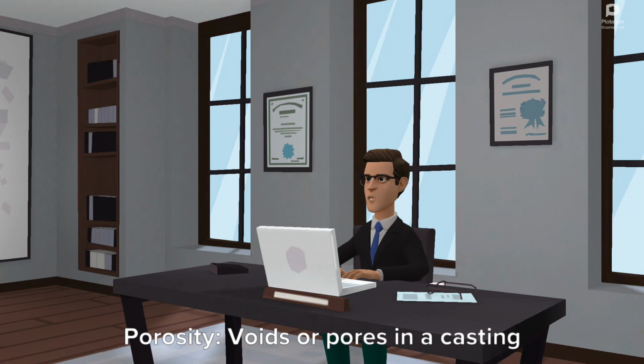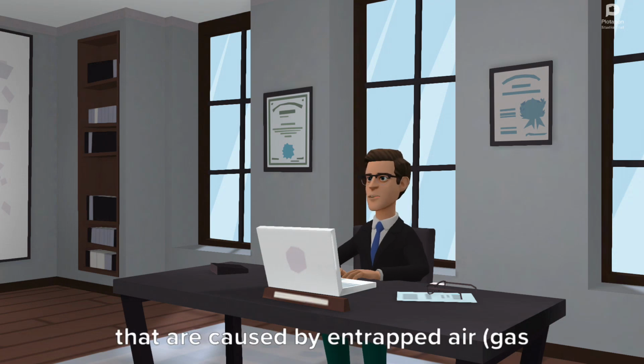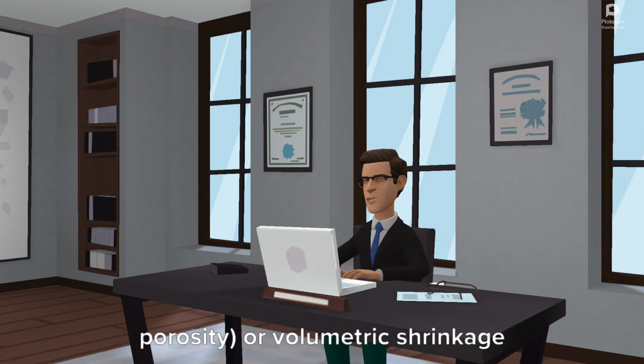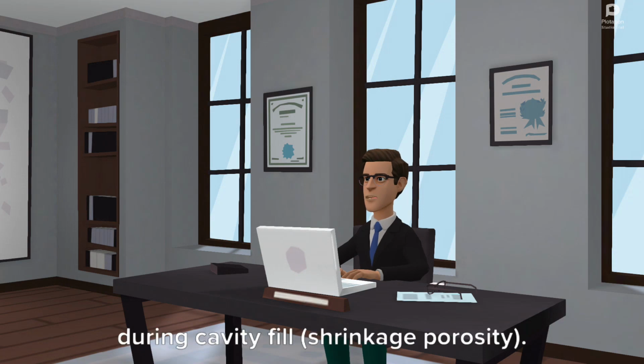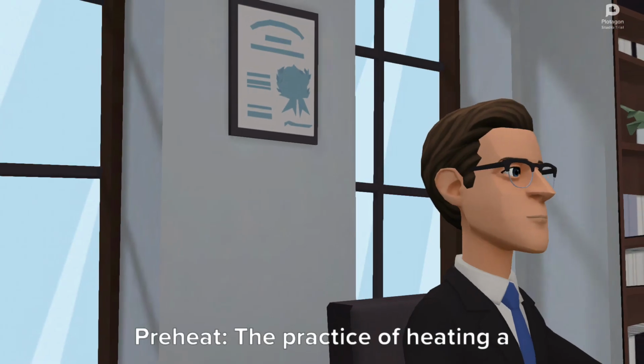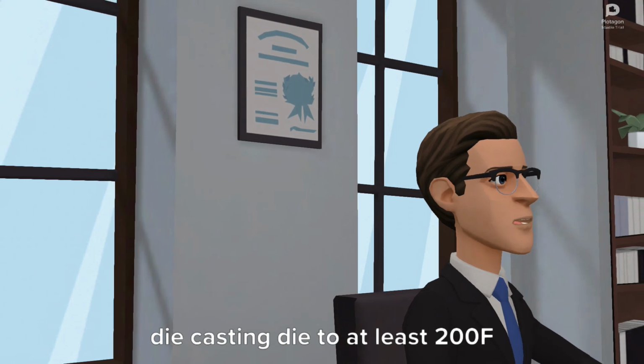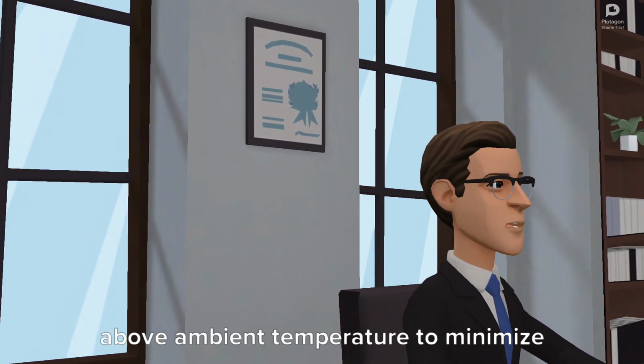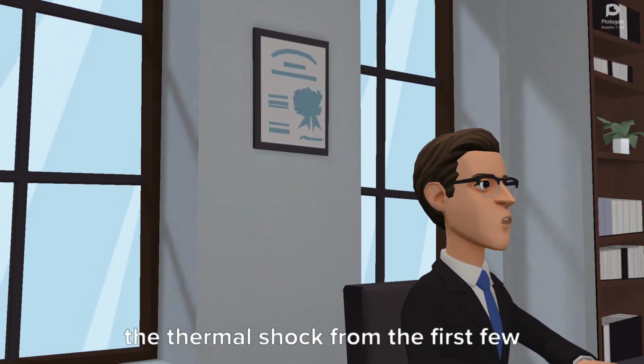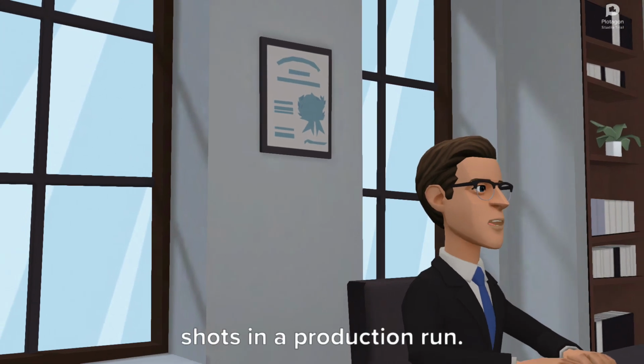Porosity, voids or pores in a casting that are caused by entrapped air, gas porosity, or volumetric shrinkage during cavity fill, shrinkage porosity. Preheat, the practice of heating a die casting die to at least 200 F above ambient temperature to minimize the thermal shock from the first few shots in a production run.